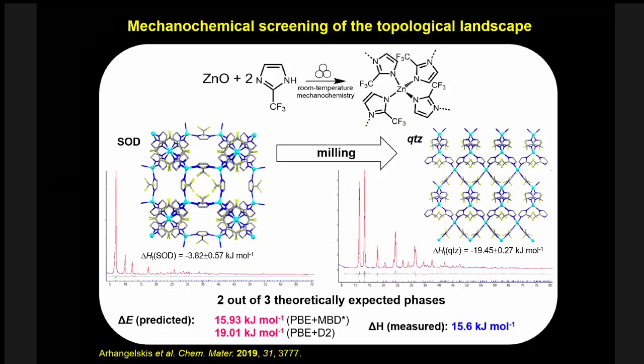This is not organic polymorphs. This is MOFs. This is some work we've done a couple of years ago, where we tried to actually predict which MOF structure we will get for this system, which was previously not really characterized. And well, predictions worked perfectly. That's all I'm going to say. But the important thing is this MOF exists in two polymorphs. One of them has a quartz structure, and this one has a sodalite structure.